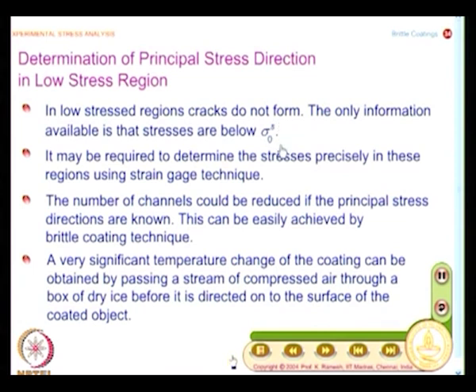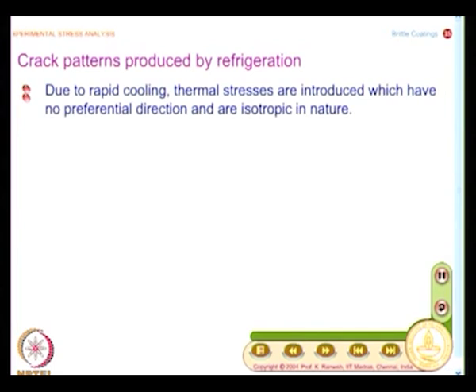And what you can do is, the next 2 points say why we need this. What you actually do is, a very significant temperature change of the coating can be obtained by passing a stream of compressed air through a box of dry ice before it is directed onto the surface of the coated object. So, what you do is you generate a cool air and then put it. So, you generate a temperature field which is isotropic in nature, and that precipitates crack formation. The general level of stress increases, and that is what you have.